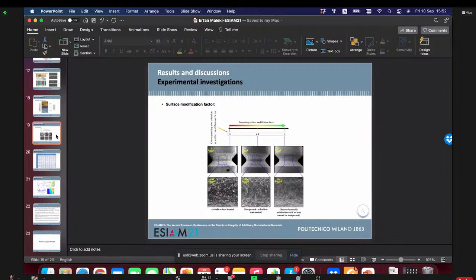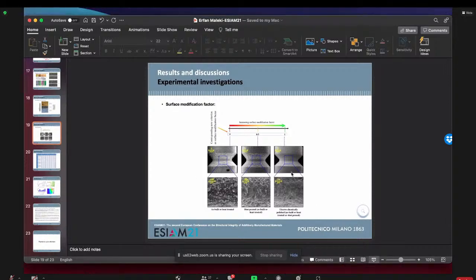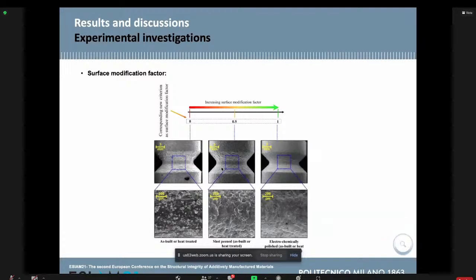Also, it was found that the fracture site, if I can show you here, the fracture site in the as-built material is above the notch root on the upper skin surface. By applying heat treatment and other treatments, it moves down toward the notch root, and by applying these surface post-treatments, we can eliminate the sensitivity of the behavior of notched samples to the surface roughness.